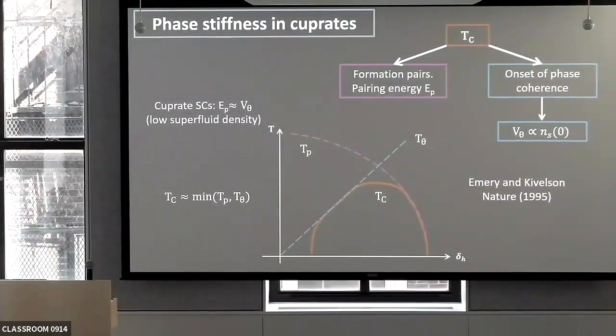So this is a conceptual phase diagram of the cuprates, with doping and temperature. Here is the dome, and this goes back to Emery and Kivelson's picture of a superconductor with very weak phase coherence. So a dome which is defined by two parameters. One is the pairing energy, the formation of Cooper pairs, the binding, and the other one is the phase coherence those Cooper pairs will have. The conjecture at that time was that in this particular system, while on the overdoped side the pairing is the defining energy scale, on the underdoped side it would be the phase coherence. So very weak phase coherence, and so Tc is really only crossed when the phase coherence is large enough.